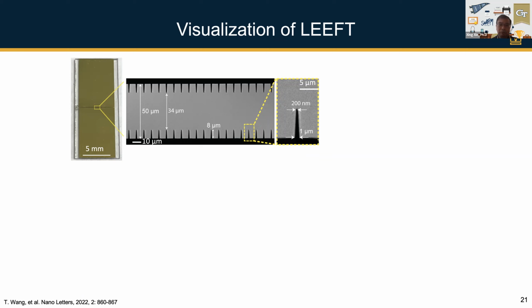We also realize that it's very important to study the cell transport inside the system, because in our system, the electric field strength is locally enhanced. So there are only very small regions in the system where you have a very strong electric field, and in other places the electric field strength is just not high enough. There are different mechanisms that can transport the cells to these regions in the system, but we still need to figure out and quantify those mechanisms. Anyway, that's what we're trying to do here. We want to visualize the system first.